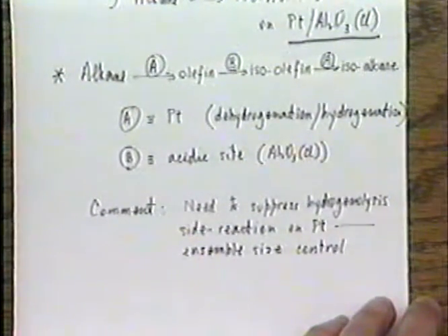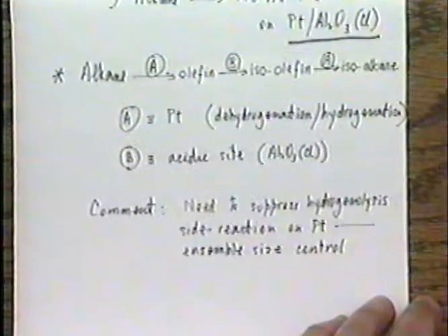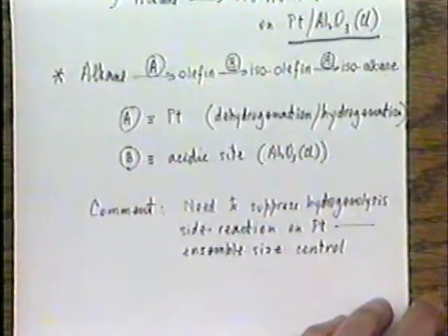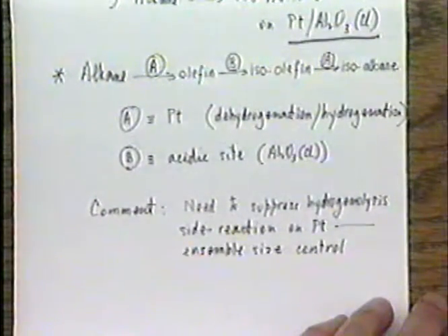If that process is tried at a low temperature, the equilibrium concentration of olefin that you will produce out of dehydrogenation of an alkane will be miserable, so you would tend to believe that you would have to run the reaction at a moderately high temperature, and in practice that's what's done. It's not uncommon for these things to run at 450 centigrade or even above that.